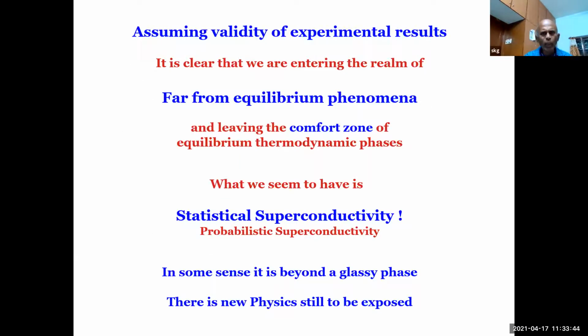So now, giving the benefit of the doubt that these are all real experiments and assuming validity of the experimental results, it's clear that we are entering the realm of far from equilibrium phenomena and leaving the comfort zone of equilibrium thermodynamic phases. What we seem to have is statistical superconductivity. That's the name I have coined, or probabilistic superconductivity. In some sense, it's beyond a glassy phase. There is physics still to be explored if the experiments are correct. And I always encourage people to repeat this experiment. Unfortunately, in the field of superconductivity, because of a lot of past history, people don't want to touch this sensitive area.